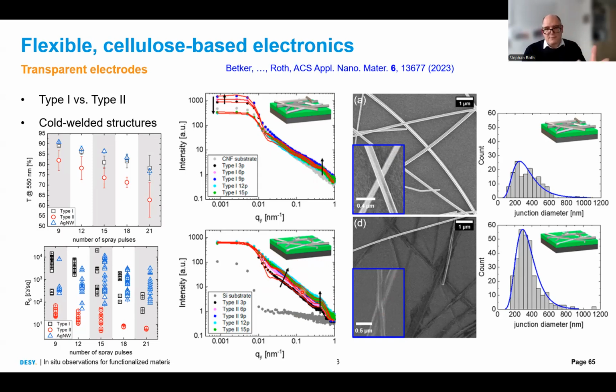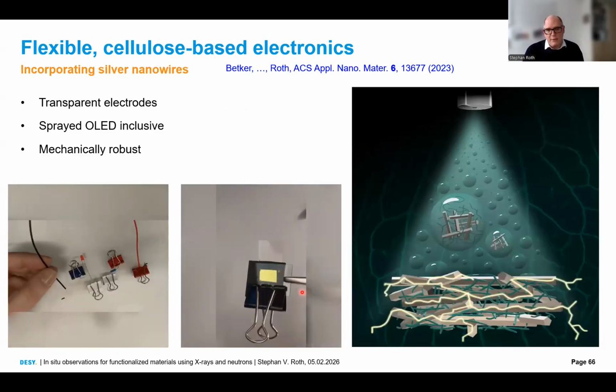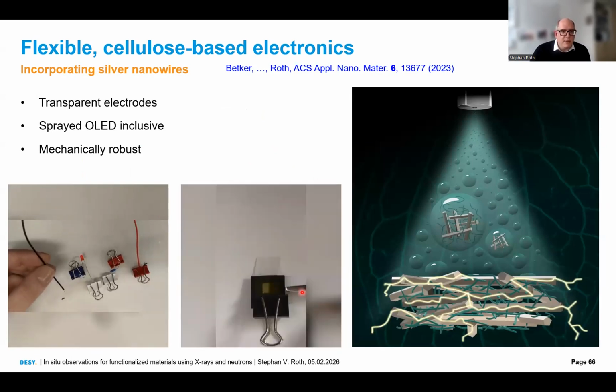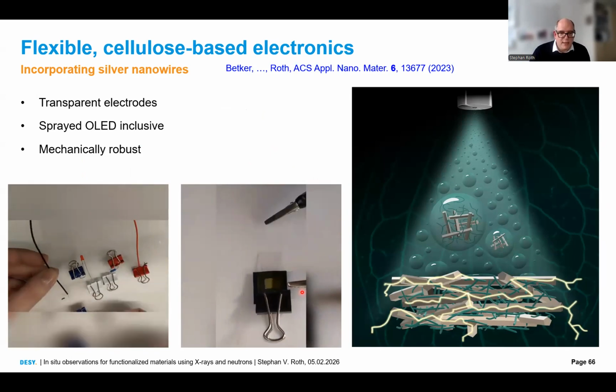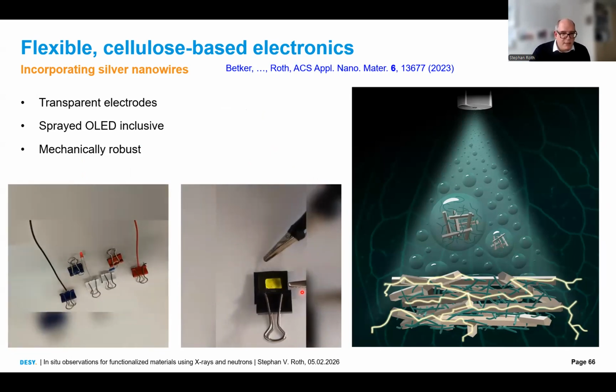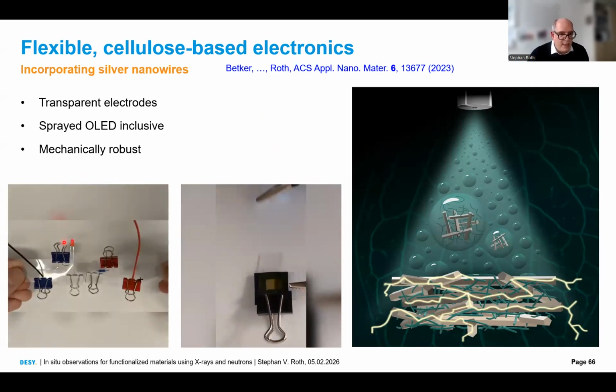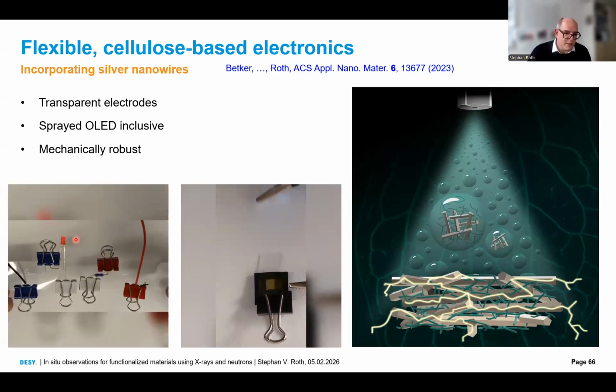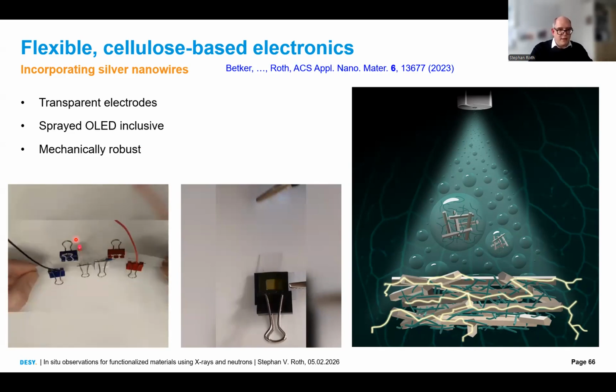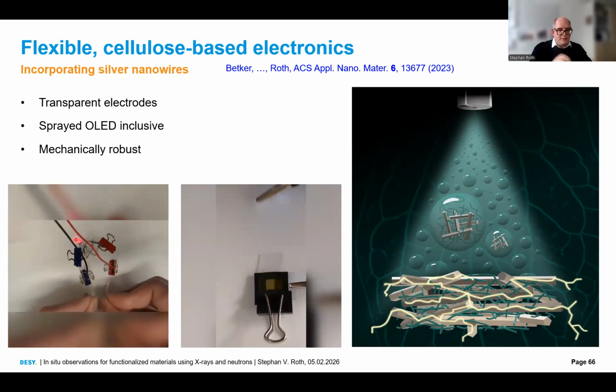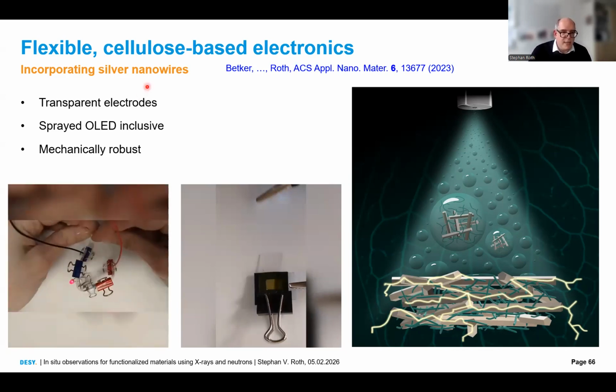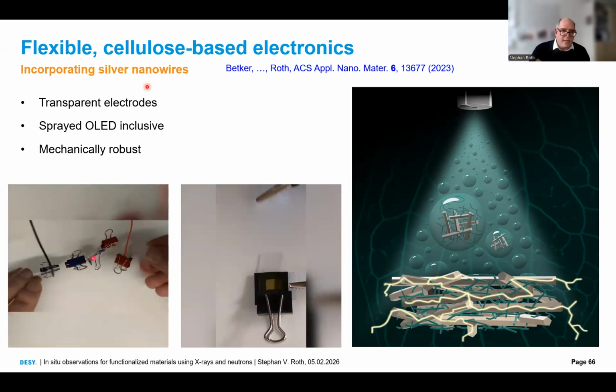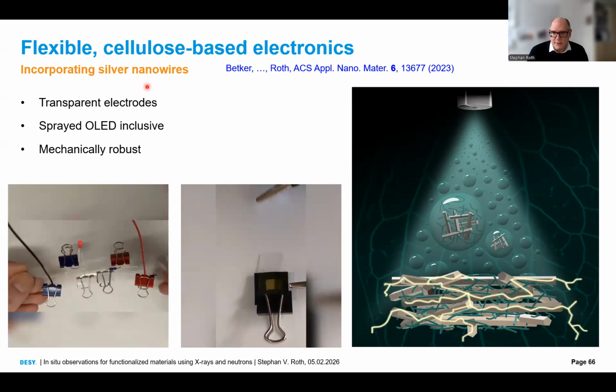So we can even explain here why we can make very good electrodes by mixing CNF and silver nanowires. And you see here they are really stable, these layers. We spray them here on PET. On the right side, you see an electrode. Here the electrode shines nicely. And on the left side, you see here an LED. My student Marie Betka, she's now postdoc in Tokyo, takes this silver nanowire layer and tortures it quite heavily, and you see that it's still really stable. You see that the LED is still shining. So again, confirming that whenever you add cellulose, you can really create stable networks under the action of cellulose.